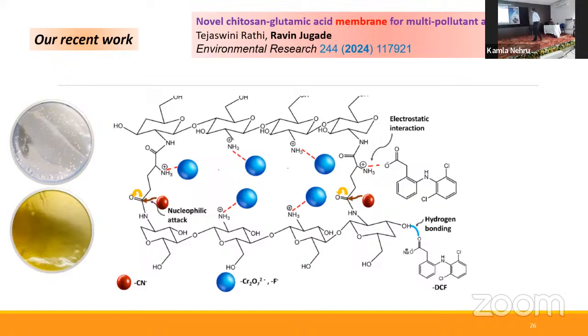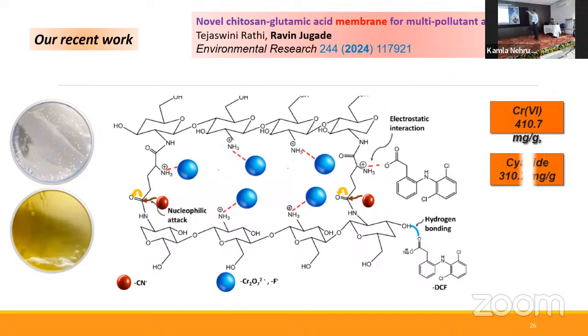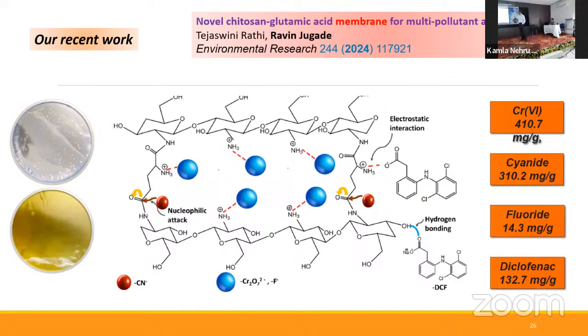Okay, so this is another way of physical modification. We have reported the membrane formed by chitosan with glutamic acid, and the membrane was used to absorb chromium as well as cyanide. You can see that the membrane is white in color, and when it absorbs chromium 6, it becomes completely yellow in color.